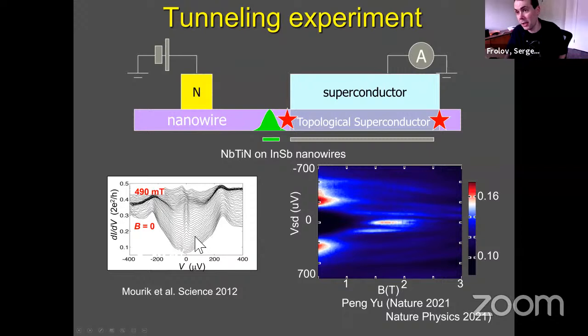What is especially appealing about this peak is that it does not move from zero bias. Here we change the magnetic field from zero to 490, half a Tesla. All these curves are just offset for clarity. At around 100 millitesla, a zero bias peak emerges and it stays at zero bias, as if the state has no spin. It doesn't disperse with Zeeman energy. Here is another example of this.